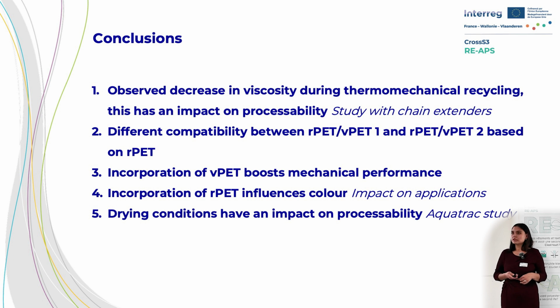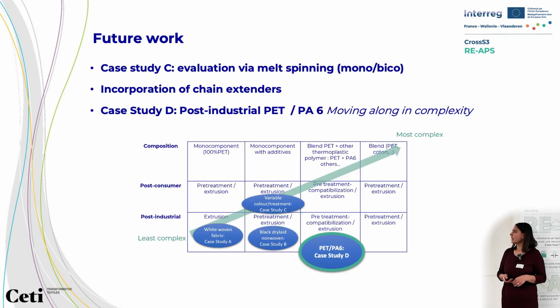And we have already seen that the drying conditions of our pellets have an impact, which helps us ensure that we are limiting this prior to this. In terms of our future work, we are continuing with case study C. We have just passed through these results. We are now going to melt spin in the way that we did other fabrics. We are then going to consider chain extenders to boost our viscosity level and make higher tenacity fibers.